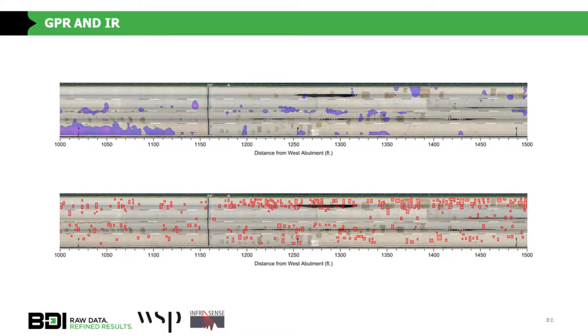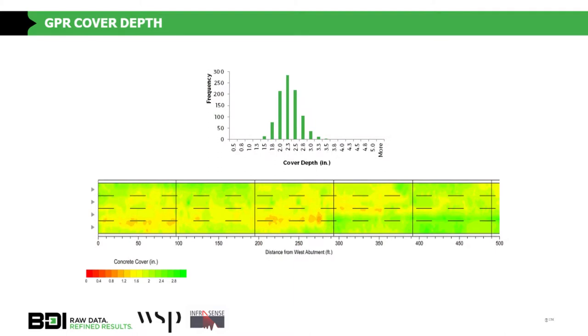Keep in mind, these examples are actually from the structure I'm discussing. This deck was very heavily degraded. The figures showing all this area of delamination were validated by going back and confirming — this isn't what you typically see in these surveys. We can also use GPR to get cover depth and a very good statistical sample of where we are with cover, so that when we apply statistical methodologies for chloride concentrations, we know where we are with regard to modeling depth.